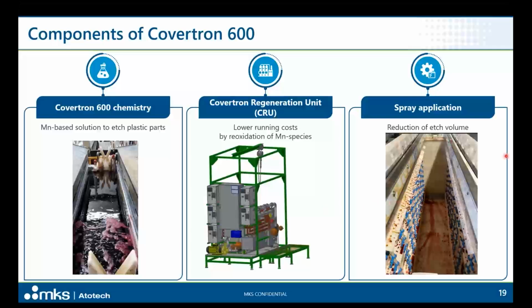And finally, we have a spray application of the etching solution. You can see here a spray booth, which is responsible for putting the etching solution in contact with the plastic parts, and in fact creates the pattern after the oxidation of the resin. Importantly, this spray application can work without producing any hazardous mist, and allows the process to dramatically reduce the volume of etching solution needed to etch our production parts, while at the same time giving us excellent metallization and adhesion results.